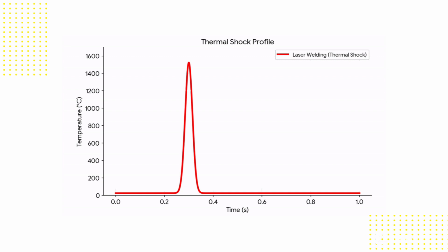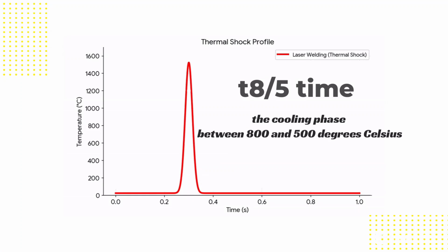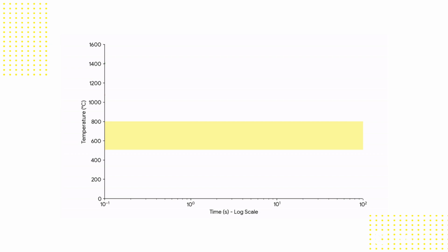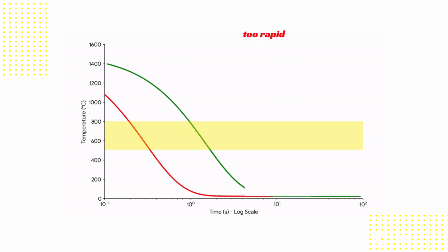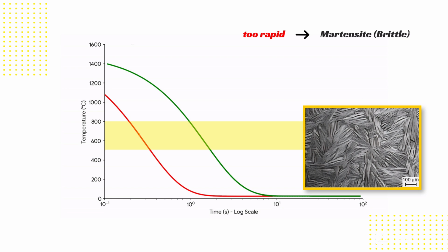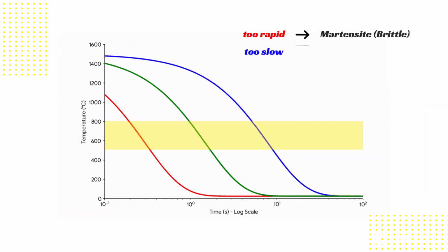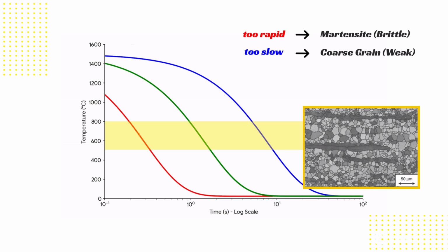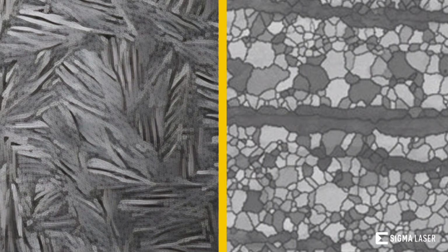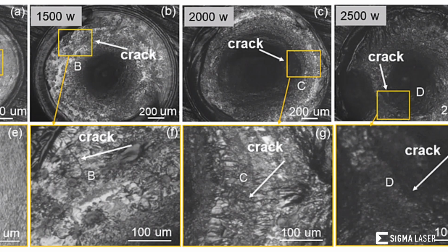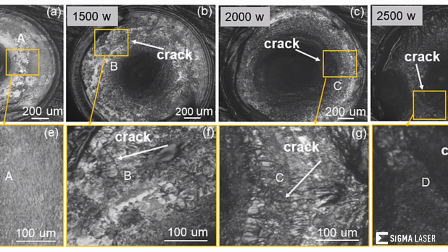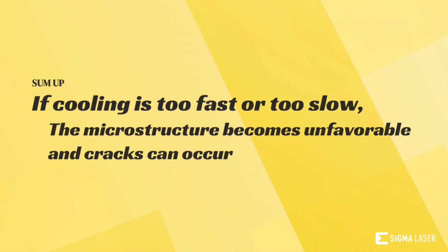These rapid temperature changes directly determine the so-called T8 to 5 time, the cooling phase between 800 and 500 degrees Celsius. Within this temperature window, the resulting microstructure is defined. If cooling is too rapid, hard and brittle martensitic structures form. If cooling is too slow, coarse-grained structures develop, reducing toughness. Both scenarios increase the risk of cracking. The problem is not the pulse itself, it is the lack of control over line energy within the weld spot. If cooling is too fast or too slow, the microstructure becomes unfavorable and cracks can occur.